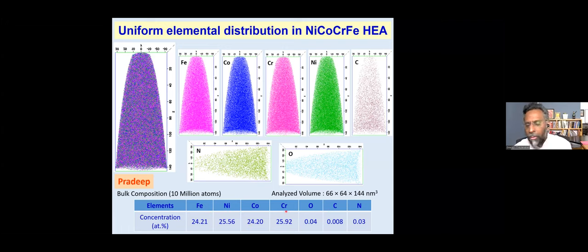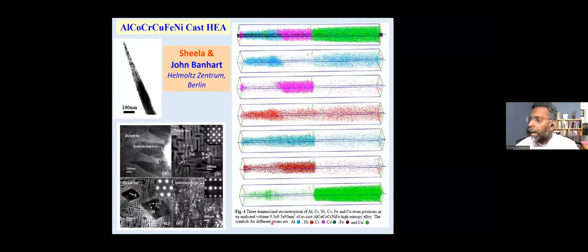All of them are very close to 25%. Just to tell you that this alloy is homogeneous. Of course, sometimes depending on the way you prepare these alloys, there can be a possibility of segregations. And when the segregations happen, atom probe can show you which element is getting segregated. That also is possible by atom probe. Atom probe is a very fascinating tool where you can know the segregation at the atomic level. This is the beauty of an atom probe.